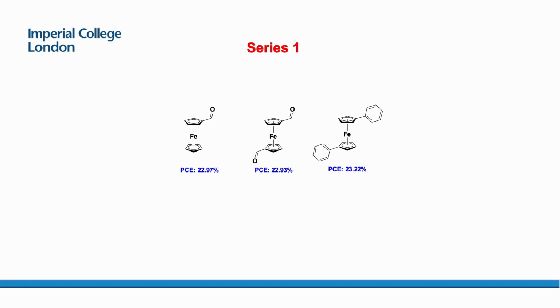So this was this chance conversation. I'm an organometallic chemist. Those chemists in the audience will recognize this material. It's basically a ferrocene. It's an organometallic material, a collection of carbon ligands with a metal center that's iron. So these are relatively commonly found. They are relatively cheap to produce, and these things are tunable in terms of we can add different functionality around the organic core. And so the PCE, the power conversion efficiency, was the number here,